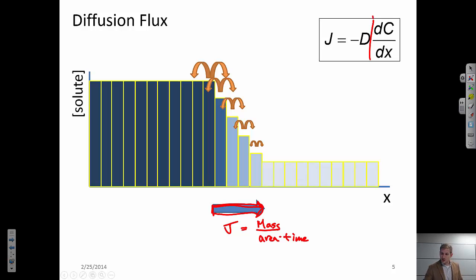This is going to be proportional to the concentration gradient dc/dx. So if I have a large discontinuity in the solute concentration, I'm going to have a large flux across that small thickness. If I have a concentration gradient that is more spread out, dc/dx is going to be smaller, so that would just be the derivative, the slope of this line. It's going to be smaller and my overall flux is also going to be smaller.